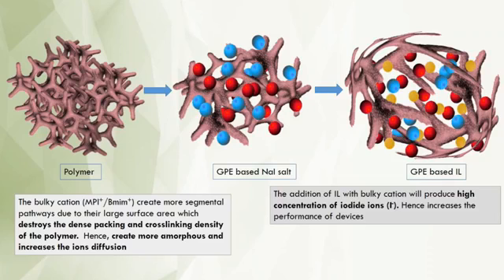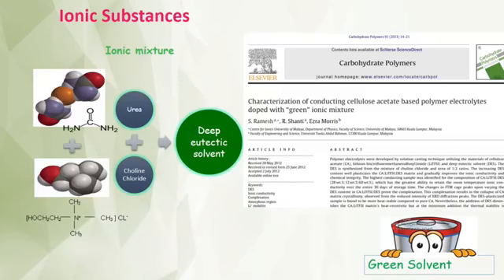Like I mentioned earlier, amorphous nature is preferred for better conduction. And also the addition of ionic liquid with a bulky cation can produce a high concentration of iodide ions and increase the performance of devices. So we also work with a deep eutectic solvent, where the combination of urea and choline chloride is used as a conductivity enhancer in the electrolyte.